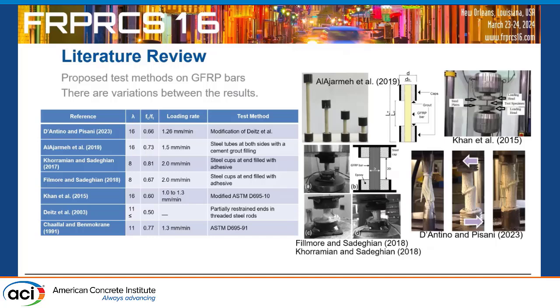Just another background is that there is no ASTM standard test for testing round FRP bars. That's the reality. So we have this ASTM, where you just put the FRP in between. It's very general. It doesn't work. And there are a couple of other ASTMs, just gripping by shear, but it's good for flat specimens. There is another one, CLC. It's a compression and shear test that provides end bearing and friction. Again, that's for flat specimens. So we are using the CLC, modifying it for the round bar. That's the story that I'm talking about.